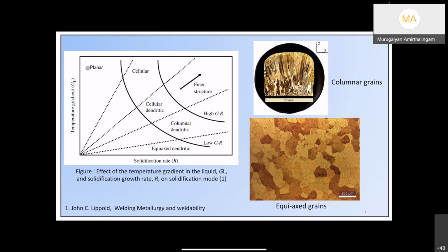Because when the temperature gradient is steeper, the melt pool, an alloy, or even a pure metal, solidifies primarily in a planar manner. So this is planar solidification. Solidification just progresses slowly from here, continuously in a planar manner. But if the temperature gradient is shallow, we get an equiaxed dendrite microstructure, what you see over here. So we understand how the microstructure morphology can change based on these prevailing conditions.